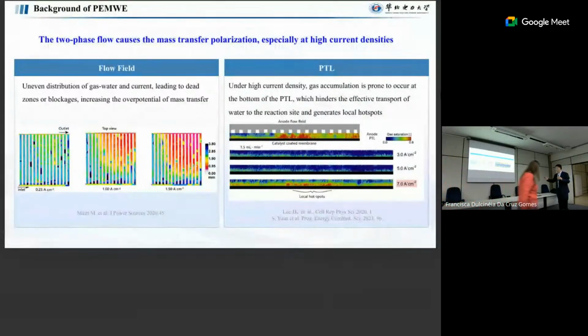And also for the PTL, we have the same. Where we have a low density, it's okay, it's blue, but where we have high density, we can see close to the catalyst a very thick layer of bubbles. Because the bubbles cover the surface of the catalyst, the water cannot come in, then the reaction stops. So that's another issue: how we can get these bubbles out.